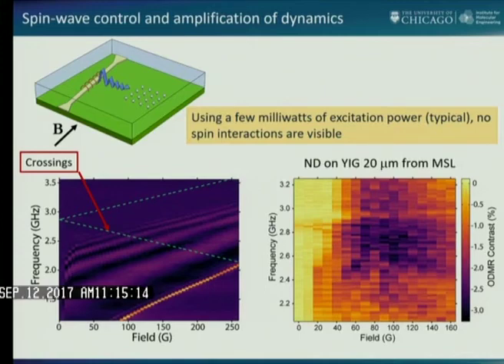So we put the diamonds on. We launched these surface spin waves. This is the applied magnetic field, and this is the frequency. This is our 2.8 gigahertz. This is where the diamond quantum state should be. This is as we apply the field. This is what you'd expect to see as the quantum state changes in energy. In this modeling, these are the spin waves moving through the material, the purple and black. And you can see that this lower state intersects lots of spin waves. They should see them. We do this experiment, don't see anything. You see what looks like a big mess here. A lot of magnetic noise, very depressing. The student worked for a long time, used a few milliwatts of excitation, which is what you typically do in resonance experiments. Nothing worked at all. Very sad moment for us.